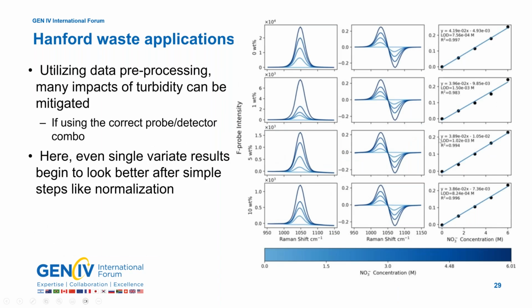The next slide shows some of the variable weight percent solids data. This is, again, sodium nitrate at 0% added solids, 1% added solids, 5%, and up to 10% weight percent solids. And we're looking at variable concentration of nitrate in each of these solutions. We're seeing very nice, well-shaped bands, so we can measure accurately the nitrate in solution. The second column shows a pre-processing step that we sometimes use, which is taking a first derivative of this curve. What that does is really eliminate the problem of any baseline noise. It transitions that to essentially zero. We get really nice, beautiful spectra all the way from 0 to 10 weight percent solids in this application.